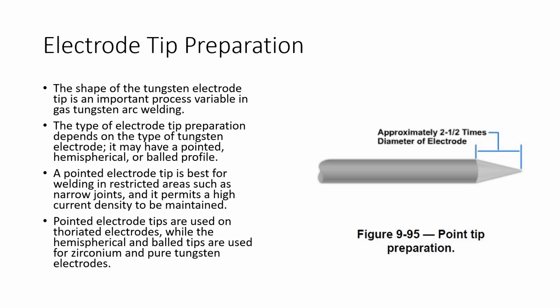When we're talking about electrode tip preparation, the shape of this electrode tip is a variable that we need to keep track of depending on what we're welding. Sometimes we're going to have a sharp tip, sometimes a hemispherical tip, sometimes we're going to have it balled up. Generally the pointed electrode tip is used for restricted areas and narrow places, and it gives us a really good current density while we're welding. So we usually use the pointed tip on thoriated electrodes, and other types such as zirconium or pure tungsten are going to get the hemispherical or balled up type. It's going to have a little rounder end than the pointed tip that we see here.